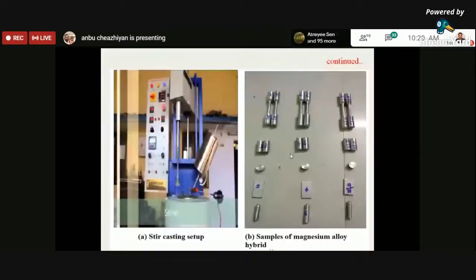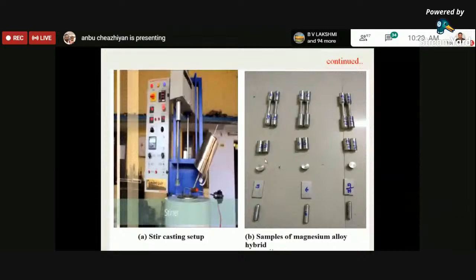So this is the stir casting setup that we have used, and these are the materials prepared as per ASTM standards. We have two sets of samples prepared for tensile, compressive, hardness, corrosion, and wear resistance tests. So these are the performance measures.